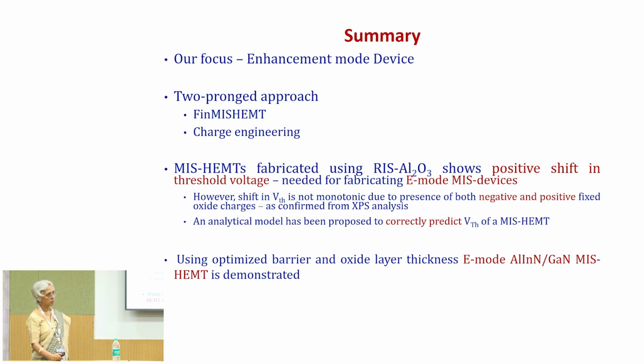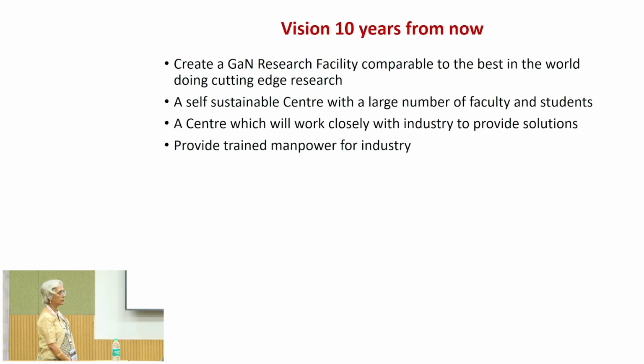And we have also done detailed analysis on why the shift in the threshold voltage is not monotonic, that is because of the presence of both negative and positive fixed oxide charges. And we have also proposed an analytical model which probably tomorrow Amita will present. So, using optimized barrier and oxide layer thickness, it is possible to demonstrate enhancement mode aluminum indium nitride gallium nitride devices. So, our vision is a long term goal.